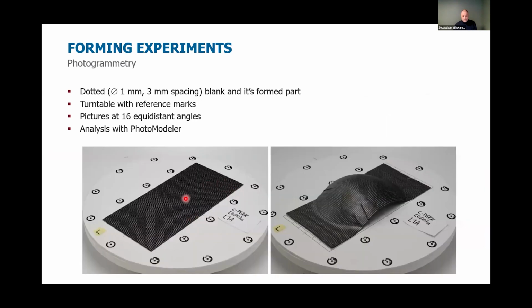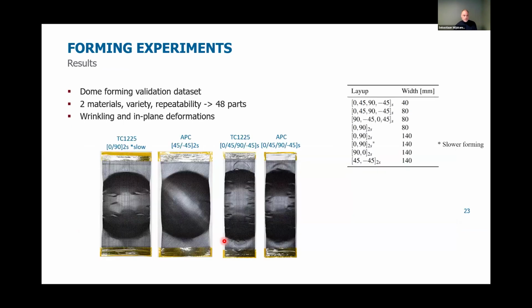For that, you need a good idea of the deformations that occur. So again, Dennis here spent a lot of time devising a way to put a lot of small dots, 1 millimeter with a 3 millimeter grid, on a laminate, and perform an analysis with PhotoModeler, so photogrammetry, before and after the stamp forming. This is a turntable with reference marks here. You have a camera on a fixed point, you rotate this table, and you get 16 pictures, and from that you can get the coordinates of the dots in 3-dimensional space.